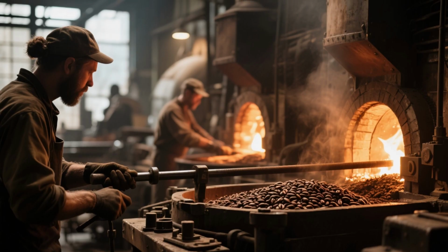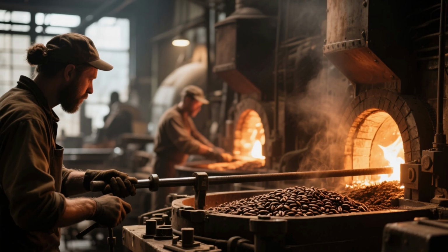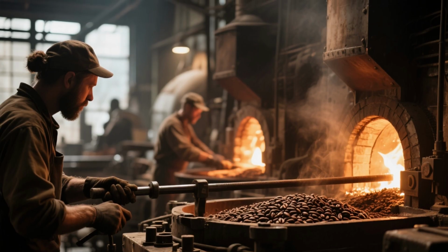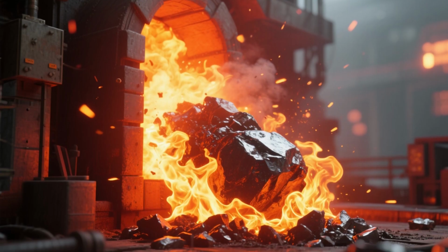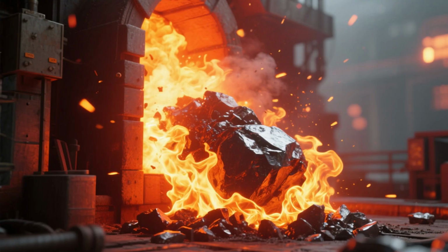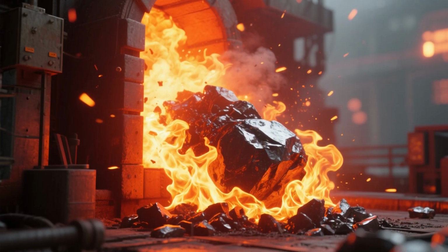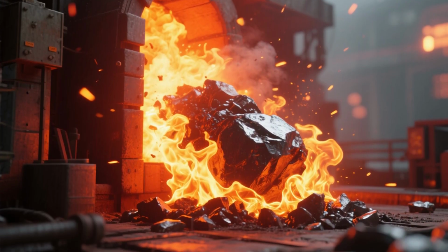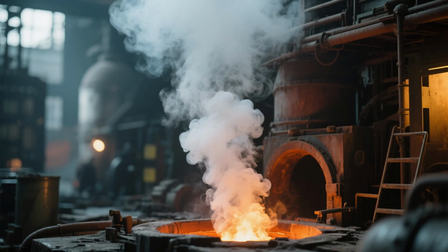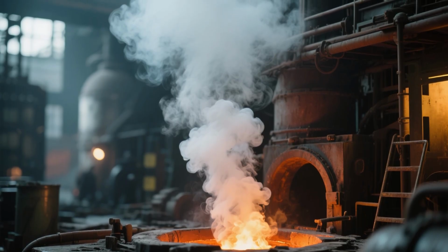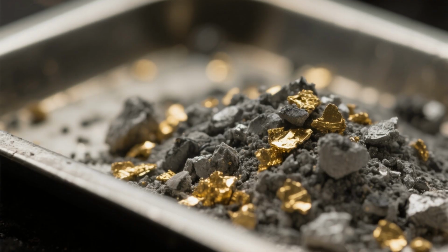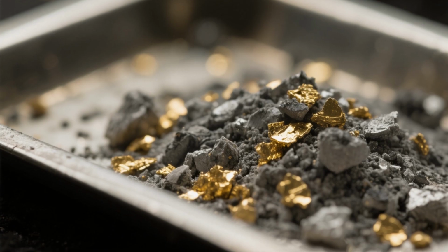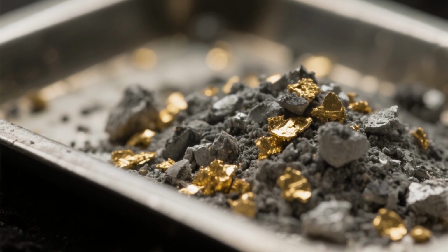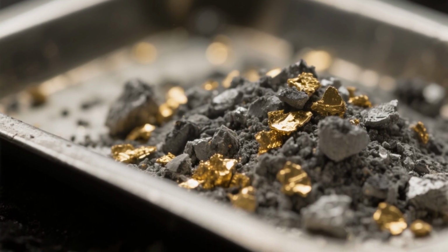Now, many gold ores have a common companion: sulfur. And sulfur can interfere with the next, most important step of gold extraction. So before we can get to the gold, we have to get rid of the sulfur. One common method is called roasting. The concentrate is heated in massive furnaces to scorching temperatures, over 600 degrees Celsius, while being blasted with oxygen. This intense heat burns off the sulfur, which is released as sulfur dioxide gas. What's left behind is a porous, crumbly material called calcine, where the gold is now exposed and ready for extraction.